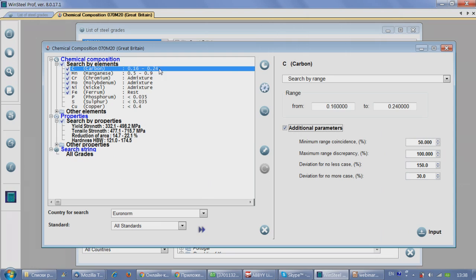So if the content of carbon in the source grade is 0.16 to 0.24, then the possible content of carbon in the equivalence is determined like this. 0.24 minus 0.16 is 0.08. Half of this interval is 0.04. So the possible range will be from 0.12, that is 0.16 minus half of the interval, to 0.28. So this coefficient means this.